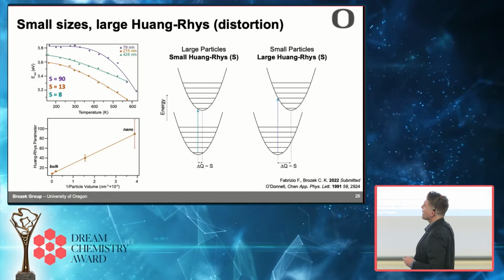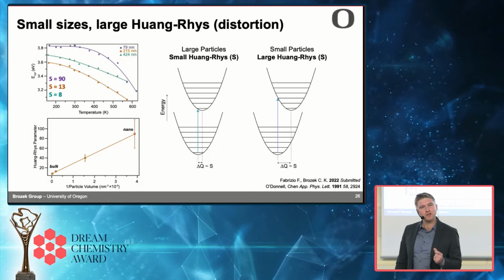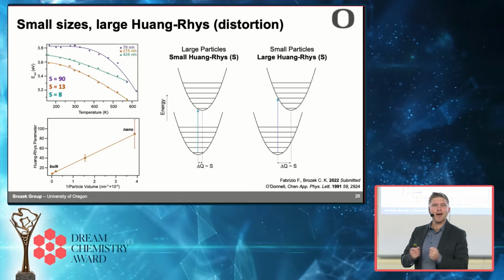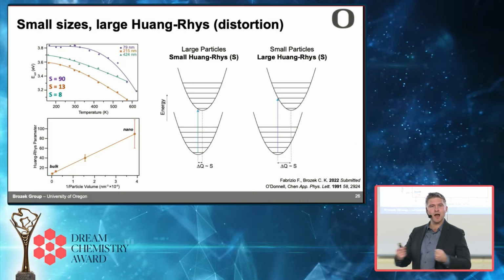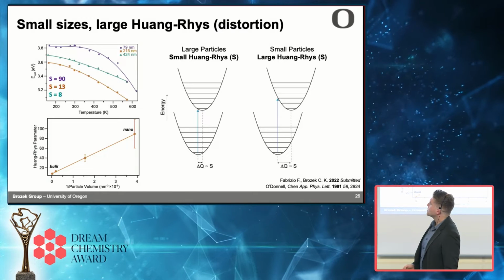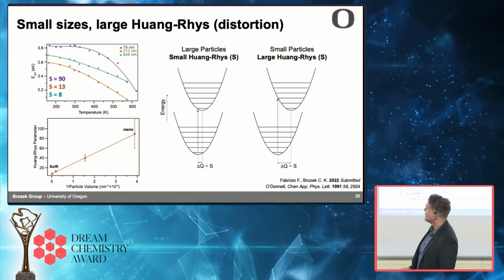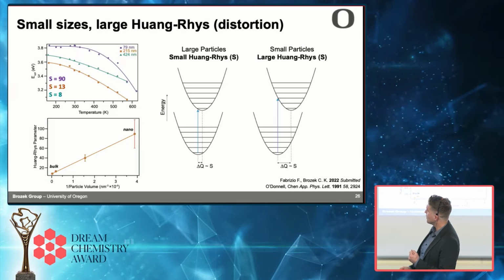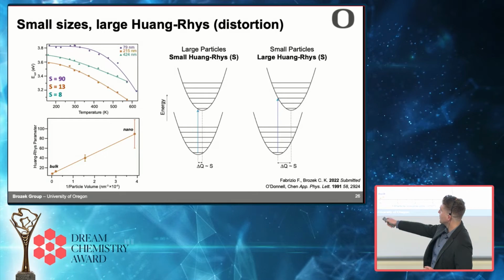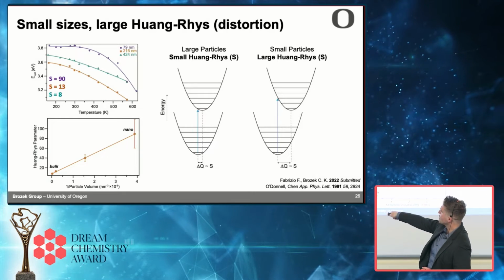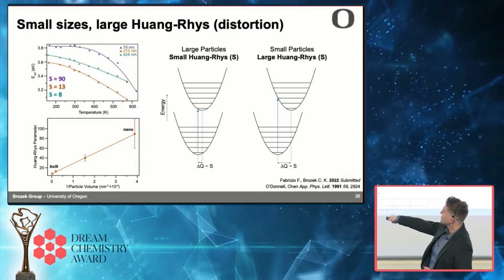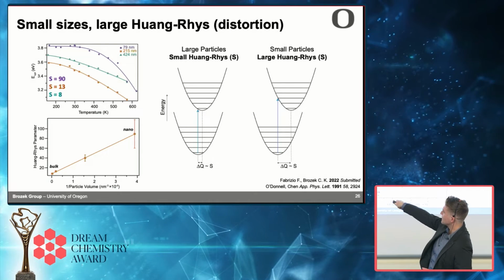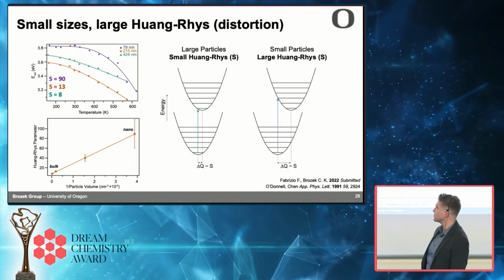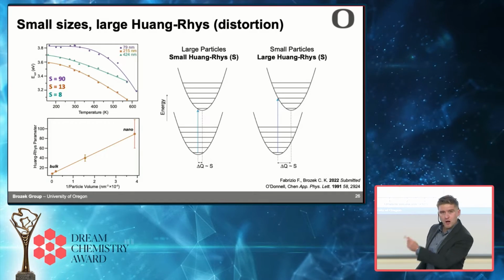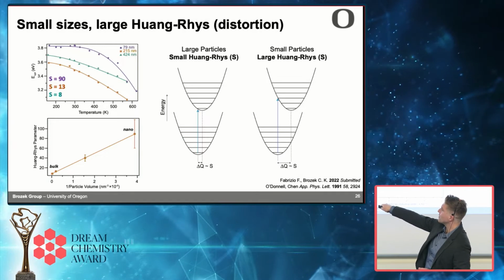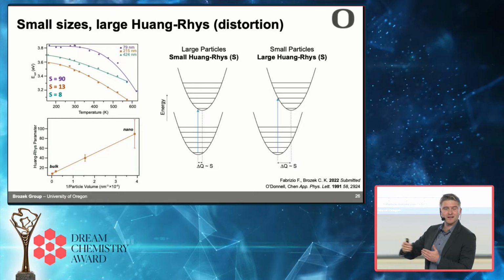So the Huang-Rhys parameter, how do we think about that? It's a measure of how much atoms are moving in your material, how much the geometry is distorting. So if you had a large Huang-Rhys parameter, as in our small nanoparticles, the geometry of your ground state is really different from the geometry of your excited state. So there's a huge distortion to your geometry. Whereas if you have a small Huang-Rhys parameter, there's just a very minor shift in the position of where your atoms are.